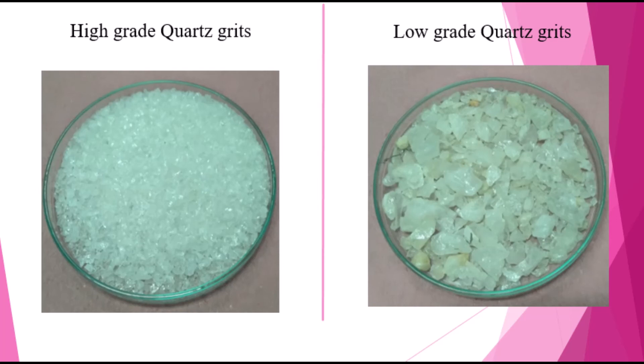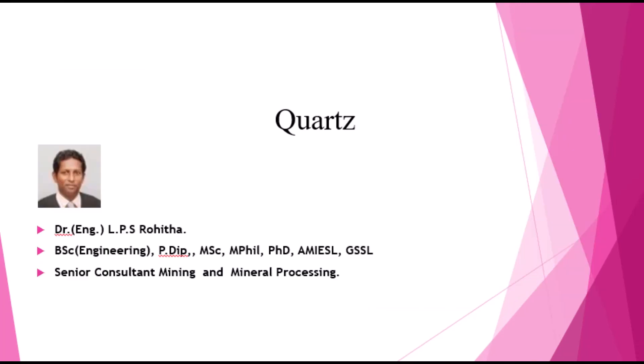The powder is subjected to a magnetic separator to remove a large quantity of iron up to a certain level. After that, we do a leaching process to further remove iron, because some iron particles remain within the quartz particles. Subjecting the material to leaching liberates more and more iron particles.